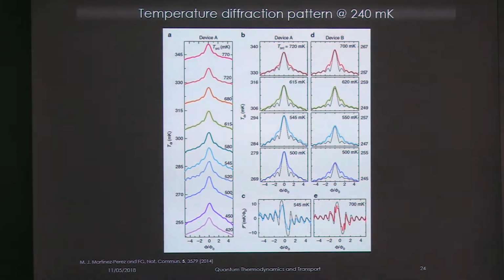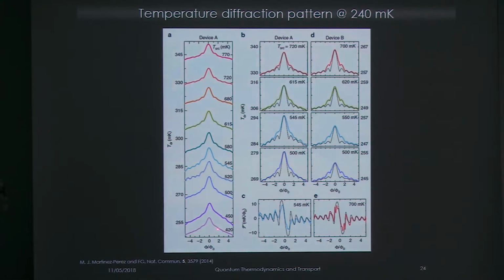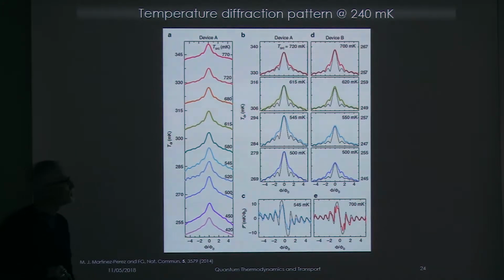If we look at the heat, it's even more impressive because you see, we start from low temperature. Okay, here is the flux through the junction, and then we increase. Of course, we set the temperature bias. Then we increase the temperature in the source. And you see that we increase the general level of current flow, and then it starts to develop these small lateral lumps that exactly correspond to this beating of the Fraunhofer pattern inside the junction. Okay, so this confirms the second aspect, that is diffraction of thermal currents in a Josephson junction.